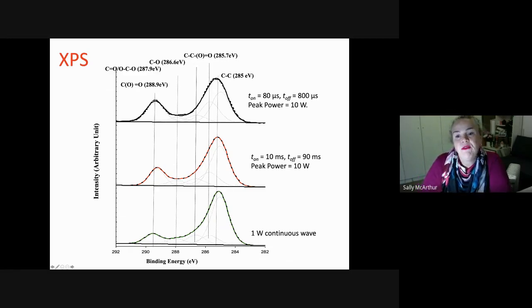But as we move through and we look at a millisecond pulsing regime, all of these, if we do the calculations, are a 1 watt equivalent deposition. So we take the power up to 10 watts, but we pulse it for 10 milliseconds on and 90 milliseconds off. So the power is delivered in pulses, and you can see that we get the introduction of more of what we are associating with anhydride groups in the film, so we get more retention of that.